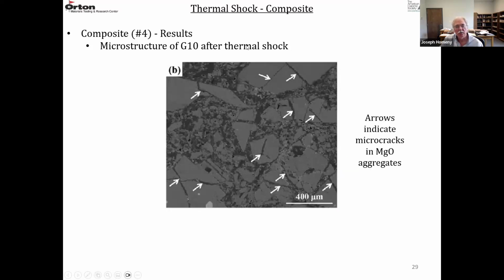And then after thermal shock, you can see all the damage in the crystals. All the arrows are indicating cracks in the MgO aggregates. So they were thermally shocked. What you can't see is all the micro cracks in the matrix. The matrix, especially at the interfaces between the carbon and the aggregates, is also micro cracked.